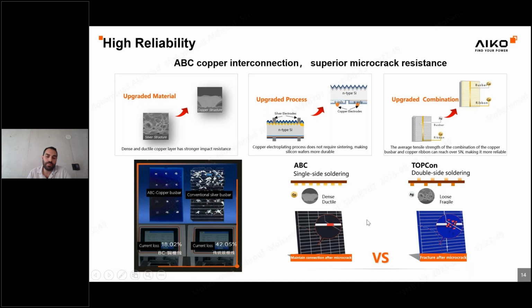And if they have, let's say, a severe crack, we have done a test just to see what's the impact if you have such a severe crack. We have seen that with the ABC technology, the loss is only 18%, while for the TOPCon, the loss in the electrical output is reaching 42%. So again, this is also a big improvement in order to reduce the risk of the microcracks and enhance the energy output of the solar system.